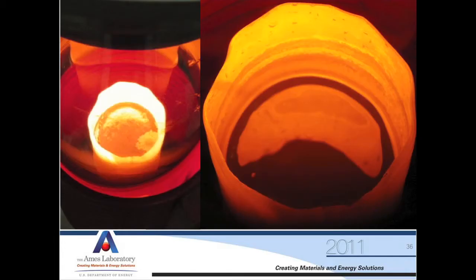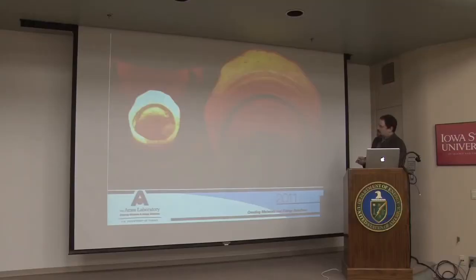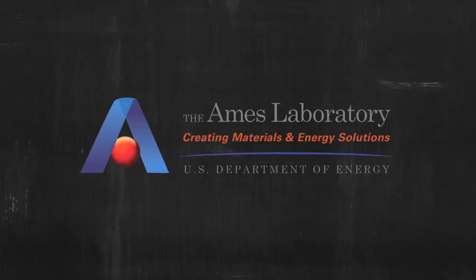This is a picture of the pouring process in action. This first one is before it's melted, and you can kind of see the texture on the surface. This more mirror-like surface indicates that it's molten, and it's partially flowed out because here is the initial level of the metal.